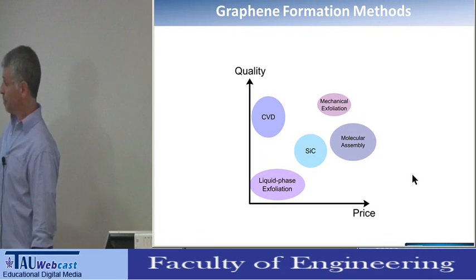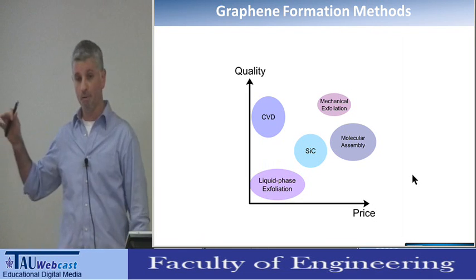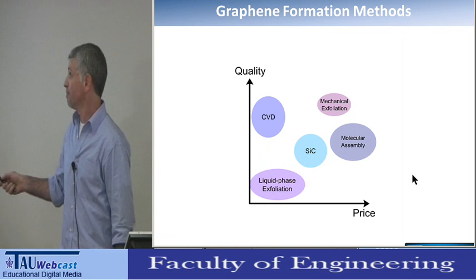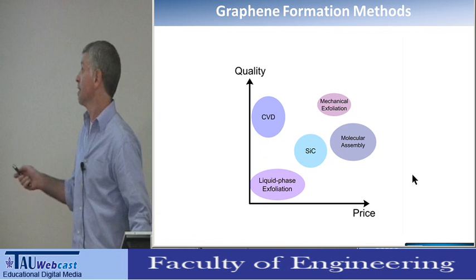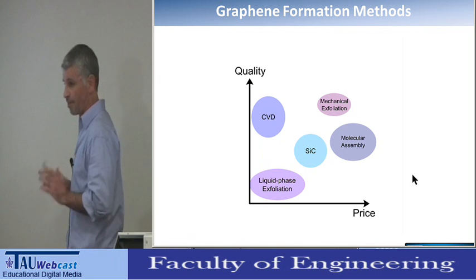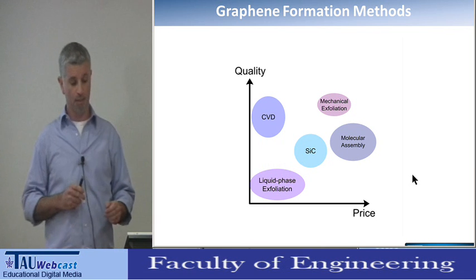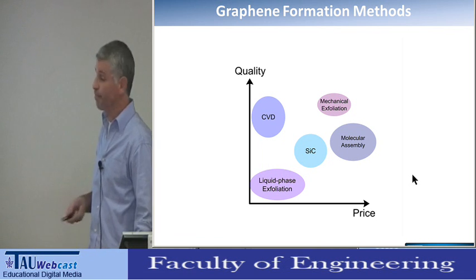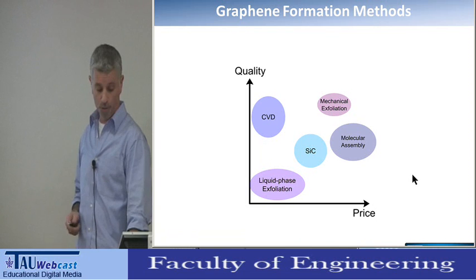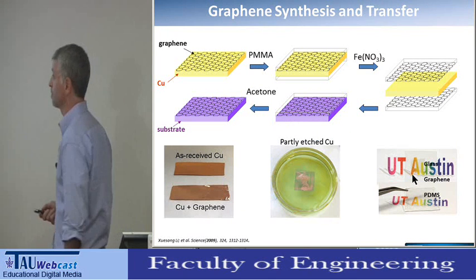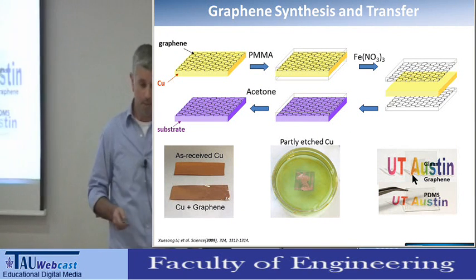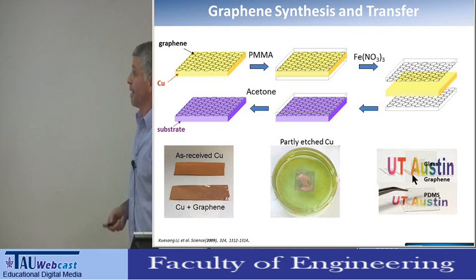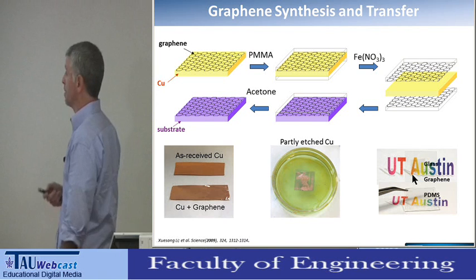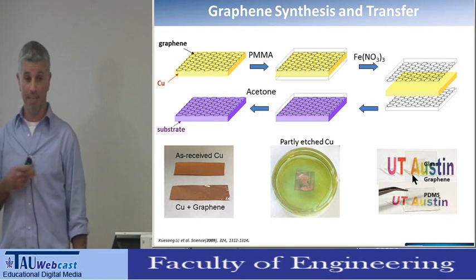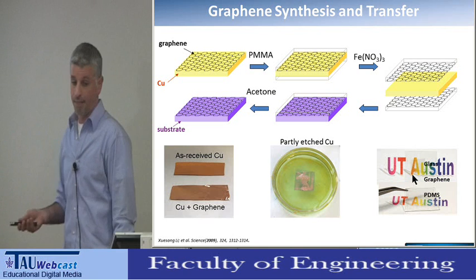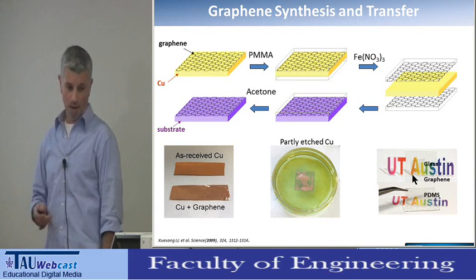And then you have the chemical vapor deposition of graphene that is constantly improving. And today, as I told you, we can achieve a quality comparable to the exfoliated one. So chemical vapor deposition looks like a very good methodology to continue studying the growth of graphene and other materials, as I will show you later. So how does it work? The graphene is synthesized on a catalyst, in this case copper, in a tube furnace where you heat it up and expose it to some source of carbon that can be anything, from amorphous carbon to almost any hydrocarbon that you can think of.